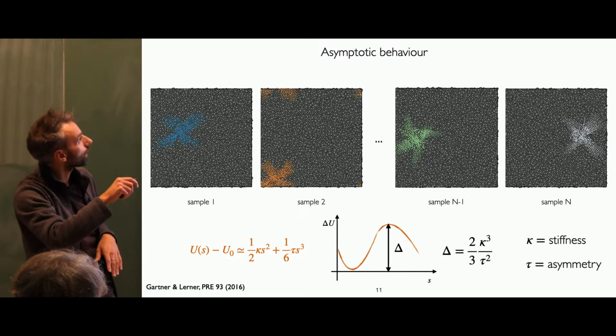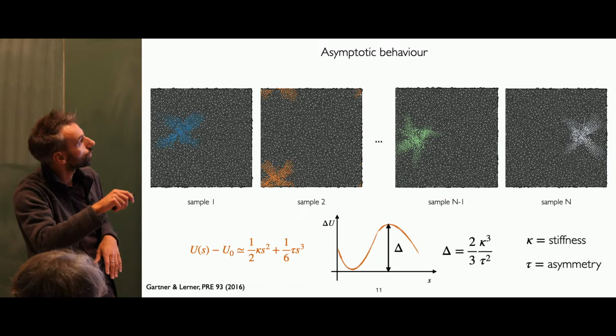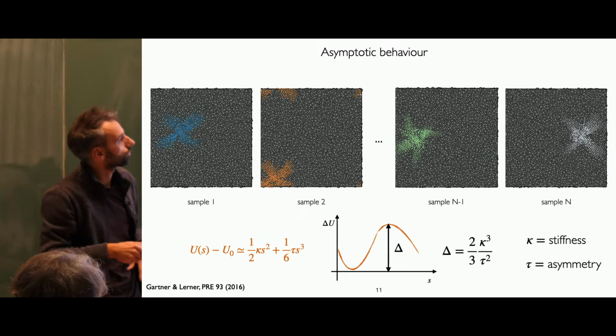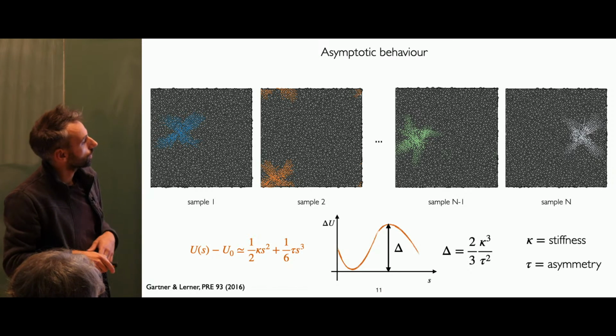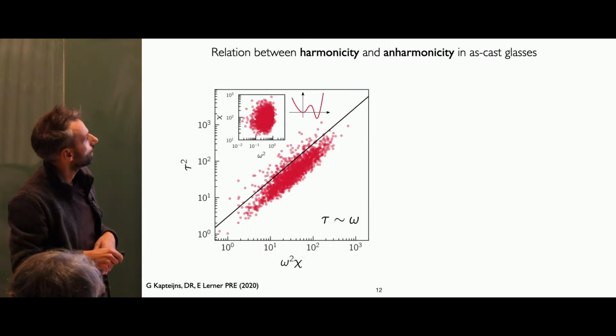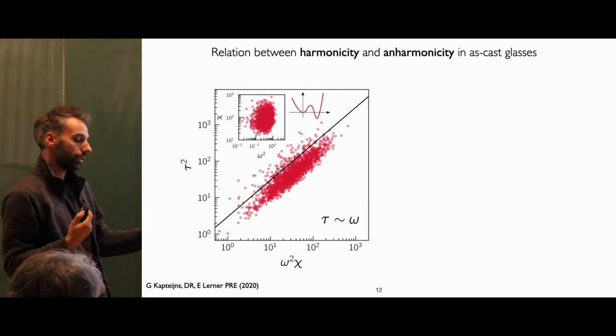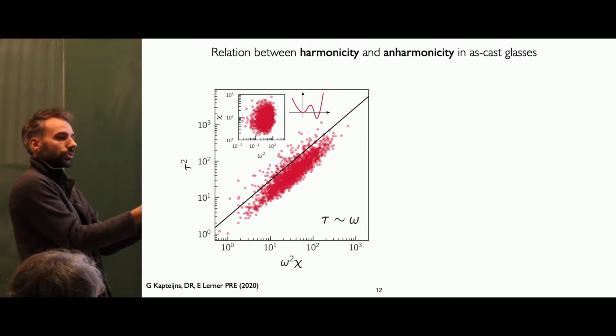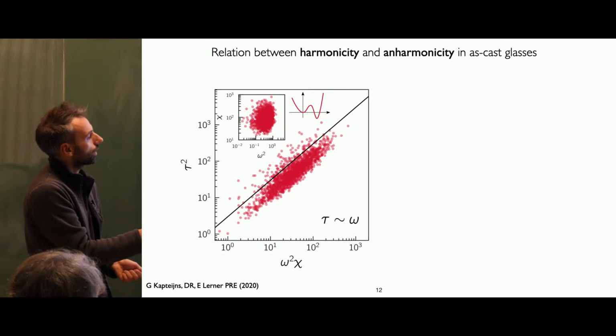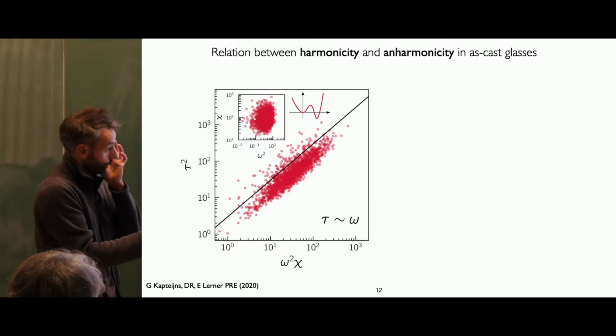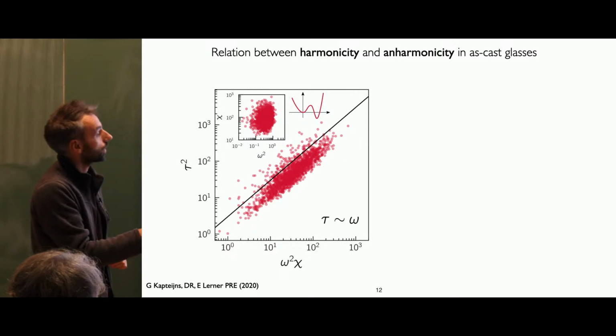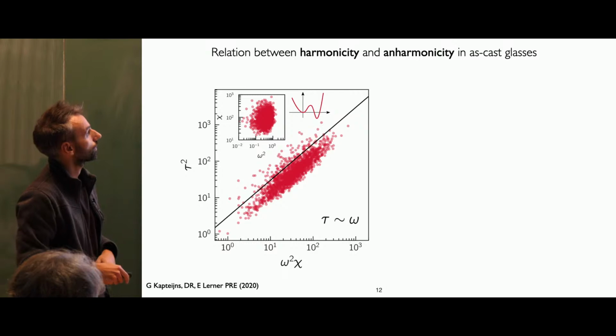And so for an ensemble of glasses, I can ask what is the softest mode in my system, if you prefer. And one thing that we realized at the quantitative level is that actually stiffness and asymmetry, or frequency, if you prefer, are related in the asymptotic regime. So if you only take the weakest spot in your system, they are actually linearly related: tau, the asymmetry, and omega, the frequency.